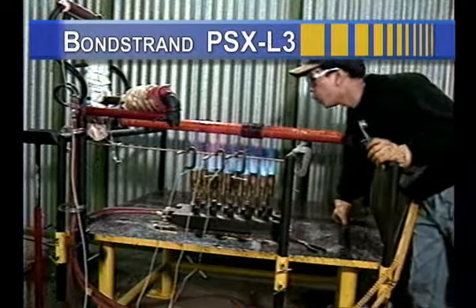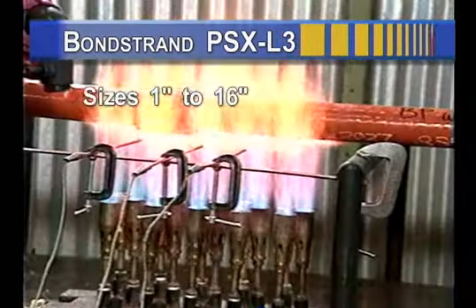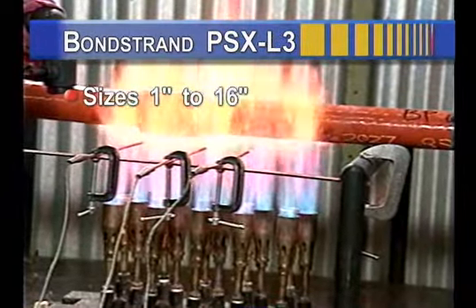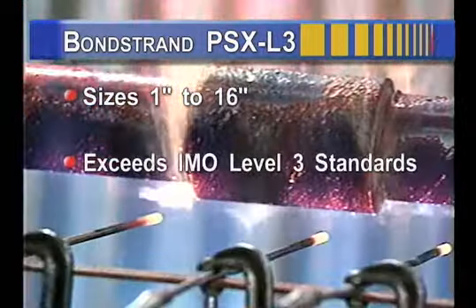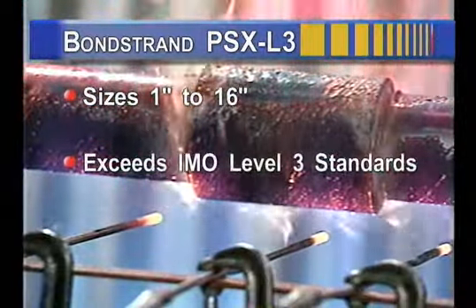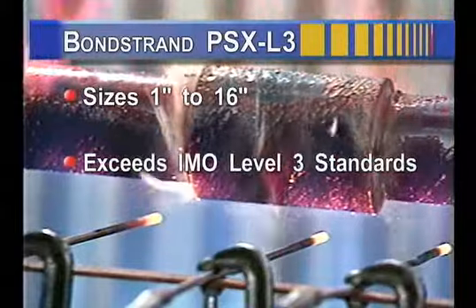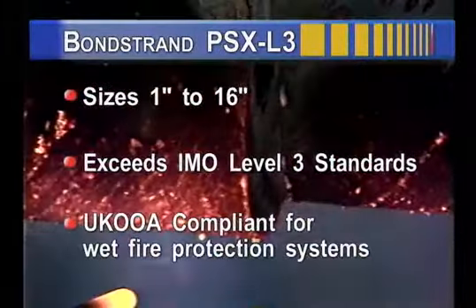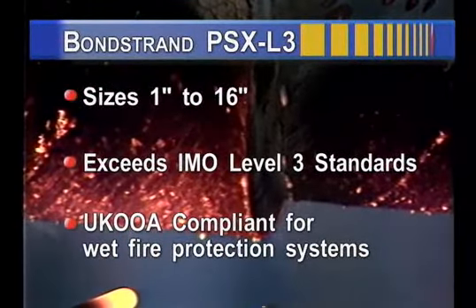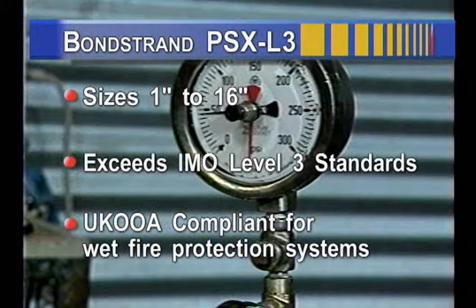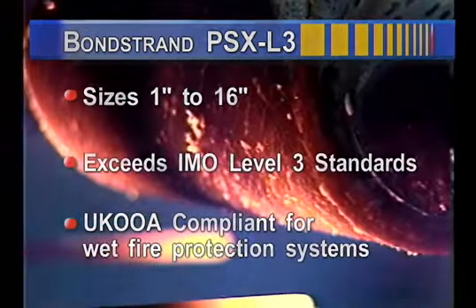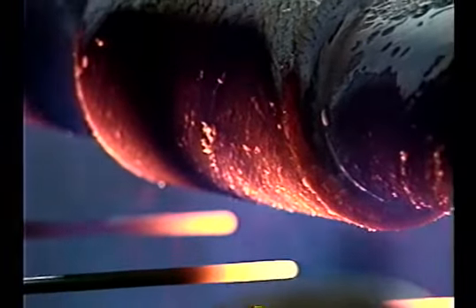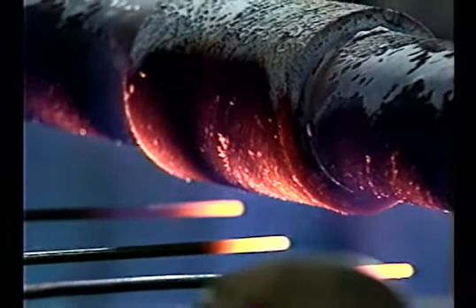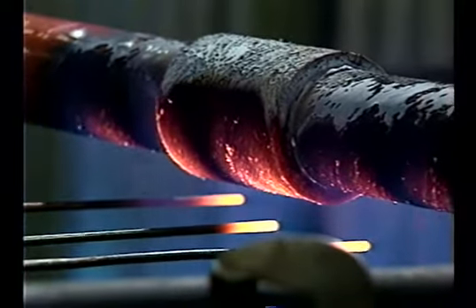Bondstrand PSX L3 is available in sizes from 1 inch to 16 inches. It exceeds the IMO (International Maritime Organization) Fire Endurance Test. Rated to Level 3 and UKOOA compliant for wet fire protection systems, this product is rated from full vacuum to 225 psi. Tested here to 1100 degrees Celsius for a period of 30 minutes, PSX L3 maintains full pressure under even these demanding conditions.